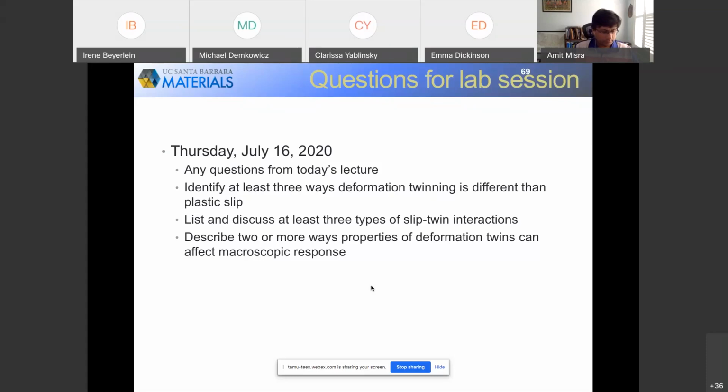Okay. So that's a very good question. One thing we can find from the basics of what we know about twin nucleation is that you need a high amount of stress and or a highly defective area. In heterogeneous nucleation, there needs to be a defect. So as far as grain boundaries, if you have, let's say, a perfect grain boundary, perfect in that it's a coherent grain boundary where you don't have any intrinsic defects,